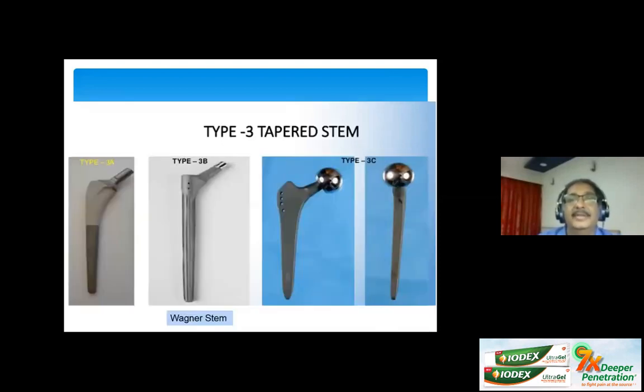Type 3, the tapered stems, and personally, and in India, we have the type 3B, which is the classical Wagner. It's a titanium tapered stem. It comes in two options, either the Wagner cone, which is a shorter stem, or the Wagner revision stem. The only disadvantage of the Wagner revision stem is that it is a straight stem. So after 200 mm, if you want a longer stem, then you are risking a perforation because the femoral bow is not accommodated, and it's then possible to use the stem after 200 mm only with some sort of a femoral osteotomy.